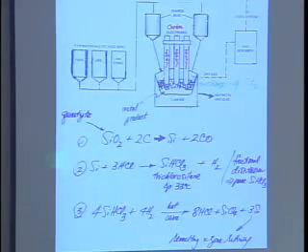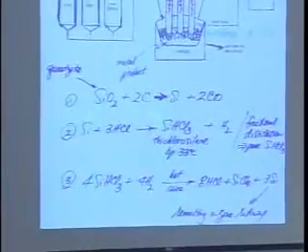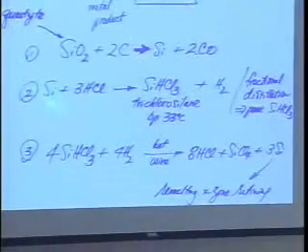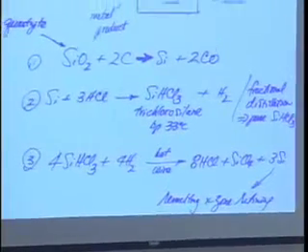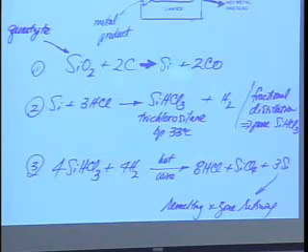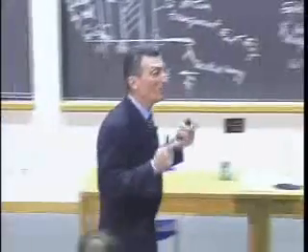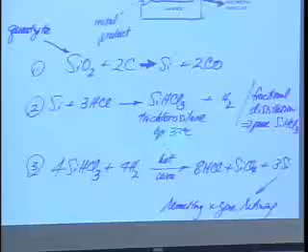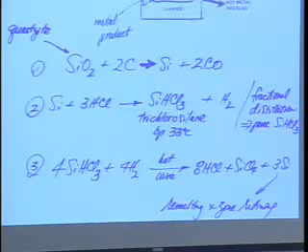So they take this impure silicon and chlorinate it with HCl. See, we've met silicon, it's sp3 hybridized. We've met HCl, and it's polar. And it forms this molecule, trichlorosilane. And guess what? The interatomic, right, secondary bonding is weak in this material, and it boils at 33 degrees C. That's below body temperature. You hold this in your hand, and the stuff will start boiling. Okay?